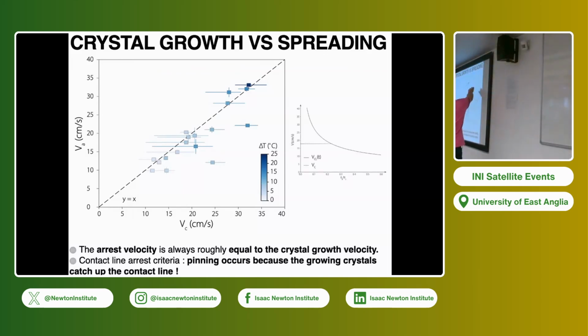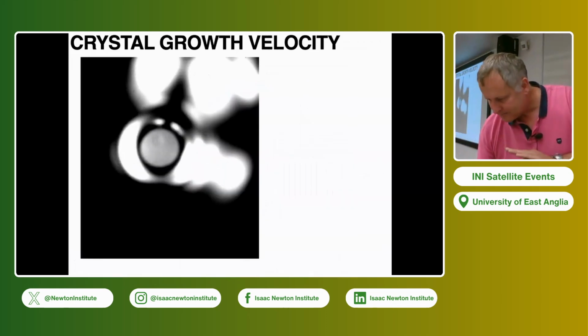Somehow the drop is spreading like square root of t, so the speed of the drop spreading goes like 1 over square root of t. On the other hand, the crystal is moving at a given velocity. So in this race, the drop can never win, because the drop is always slowing down as it spreads like square root of t, while the crystal goes at constant speed. So there is always a time at which they will touch. And actually, that's what we have checked.